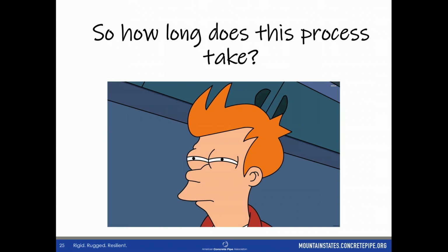Anything over 5/100th of an inch is going to have some issues, right? Because it's almost too thick and you've got almost too much water coming in and pushing against it. So 5/100th of an inch is about the threshold of what we've noticed that this will actually work. And so your larger cracks, your 10th of an inch cracks or greater, it's really, really questionable whether this will take hold and work. But it all depends on how long it takes. It depends on how big the cracks are, okay?